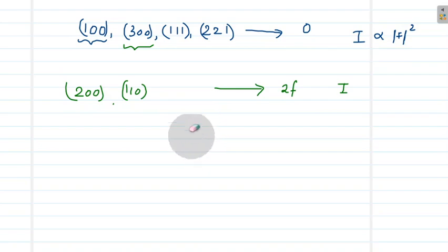factor will be 0 for a BCC lattice, and hence you will not get any diffraction beam corresponding to these planes. And if H plus K plus L is an even number, then for those planes in a BCC lattice, your diffraction intensity will be maximum, or scattered amplitude will be maximum. So that is the concept of structure factor. This is how effectively the structure affects the diffraction intensity. Even when the planes are scattering the beams, the overall structure is affecting the amplitude of the scattered wave.